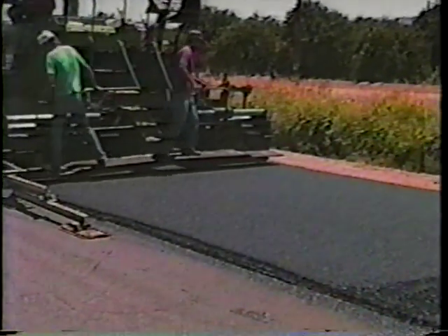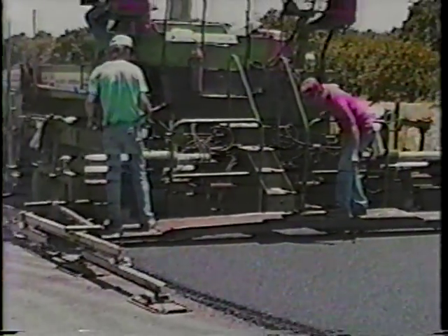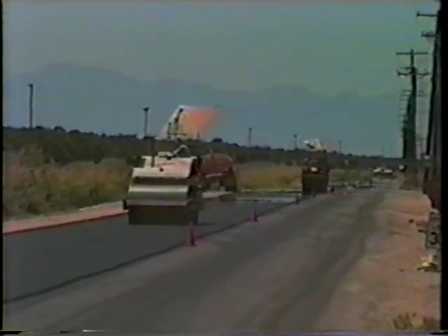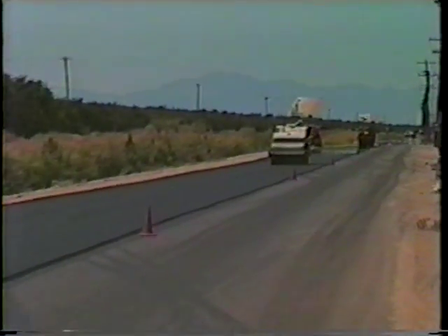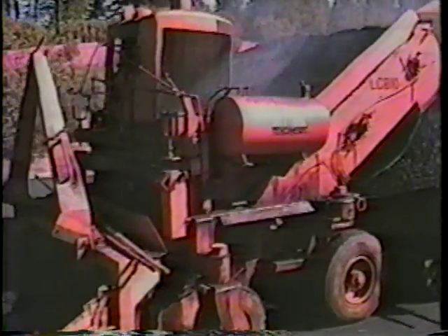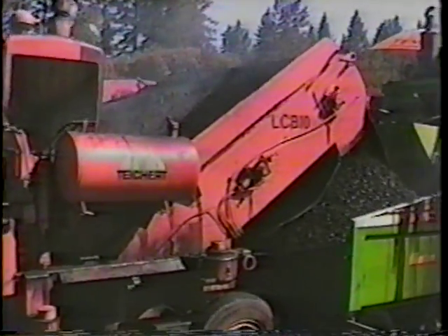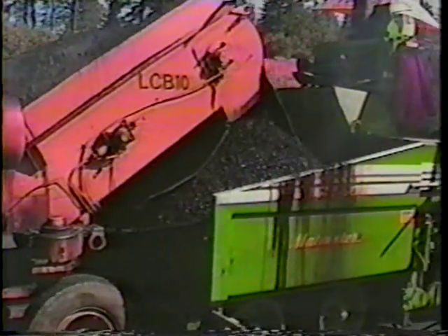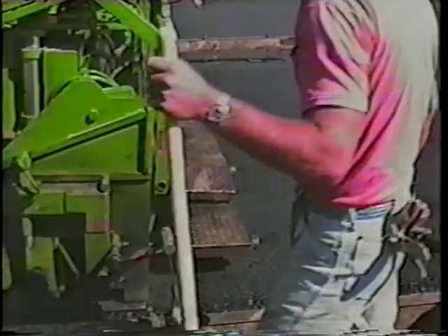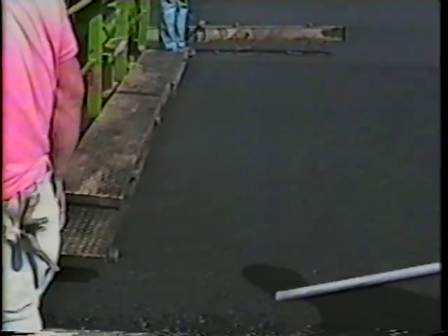Asphalt rubber concrete is essentially a dense or open-grade asphalt concrete mixture, except the binder is a reacted asphalt rubber blend instead of conventional asphalt cement. It provides a more durable asphalt concrete with better stability and is highly resistant to oxidation and cracking. Using asphalt rubber as the binder for asphalt concrete mixtures increases pavement life because of the film thickness and resistance to binder oxidation from the antioxidants and carbon black in the rubber. The higher viscosity of the asphalt rubber binder increases resistance to permanent deformation, while the elastic characteristics provide increased resistance to reflective and thermal cracking.